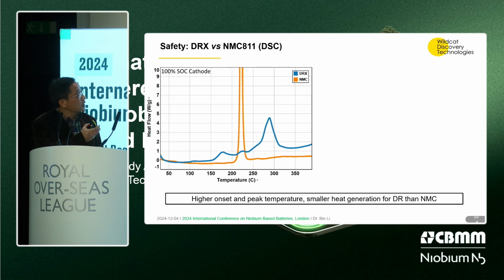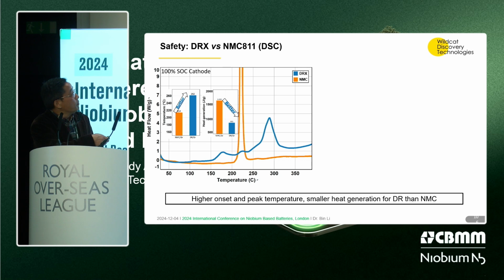Two more things that I want to emphasize for this DRX material: the safety compared to the 811. Here is the DSC based on the cathode. You see here with NMC, you have the heat generation in a very short time, which can easily trigger thermal runaway. And for the DRX, the heat generation is much slower. And more important, if you look at the onset temperature, DRX is much higher than the NMC 811. And the total heat generation of DRX is much lower than the high nickel 811.